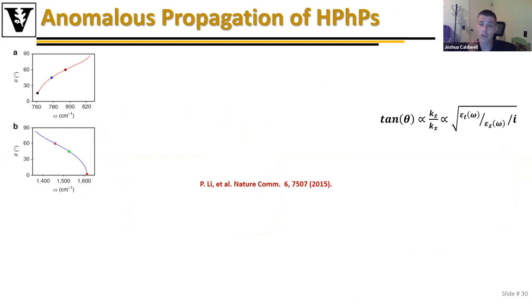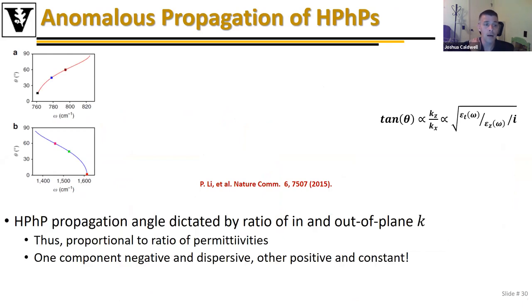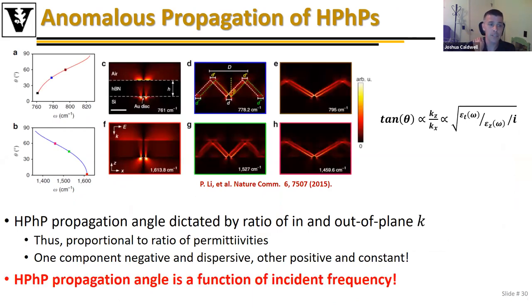Now, what does that actually look like when I talk about that angle of propagation? So in this work, in collaboration with Thomas Taubner, we explored this a little bit for the hyperlensing concept, but the key idea here is the angle of propagation is proportional to the square root of the ratio of the permittivities, the in- and out-of-plane. Right? Now, because one of these is negative and highly dispersive, the other is positive and nominally non-dispersive, this means that this angle of propagation becomes a function of frequency within these two Reststrahlen bands.